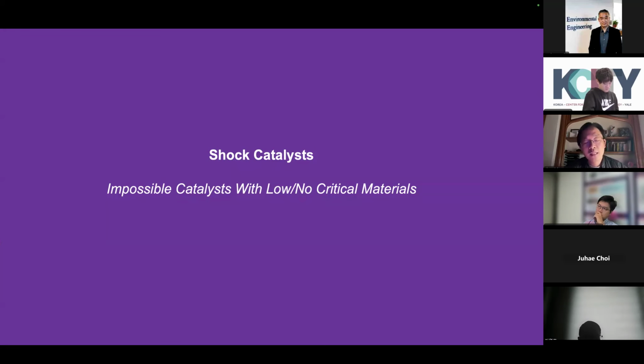So in this case, I'm going to show you how we can use a very unique shock process. It means everything happens very fast. You heat it up, you melt everything, you quench it down right away. You can lock in a lot of compositions that are not possible in traditional catalyst discovery. And very often we're trying to address critical materials, because a lot of the good catalysts, for example platinum, are very expensive and are considered critical materials, right?